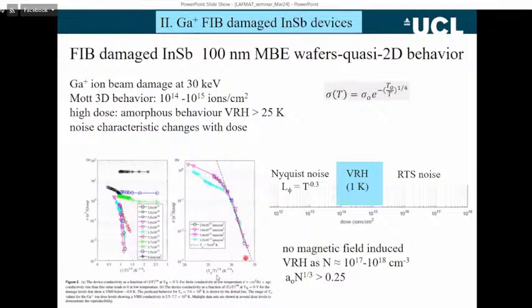Now, if we plot that out again as a function of T0 over T, so T0 is a characteristic energy associated with this hopping process, it goes over to a kind of a universal behavior for this effect. So although we've started with a very, very high carrier density, we've been able to introduce this variable range hopping effect. And this diagram here just shows a little bit more detail about what's going on in these wafers. We have ion beam dose here on the x-axis.